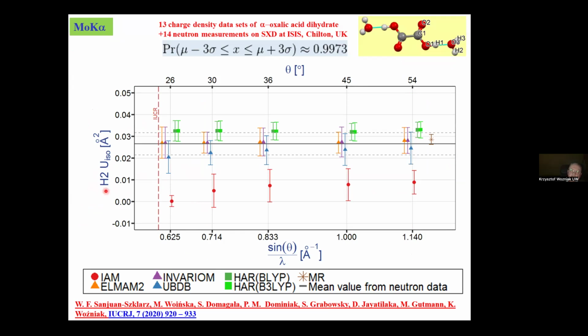But when we take the atomic displacement parameters, we see that there are systematic differences between isotropic atomic displacement parameters from Hirshfeld atom refinement and neutron refinement. And in the case of the lowest resolution, we had to use constraints because we were unable to refine freely this isotropic ADP for this hydrogen atom.